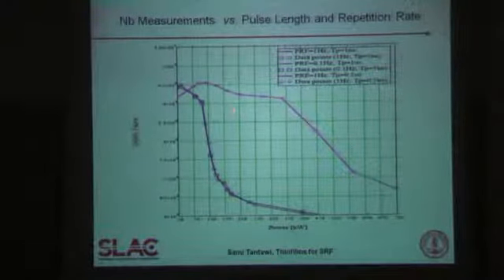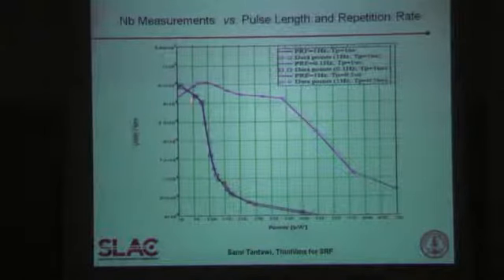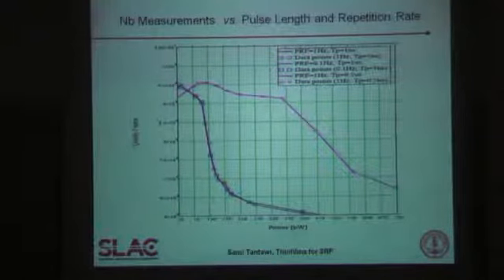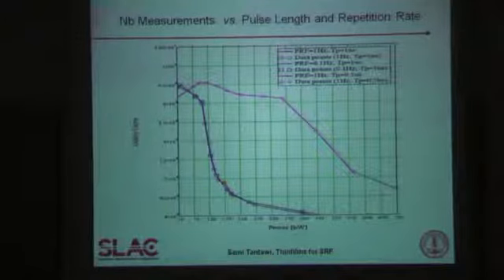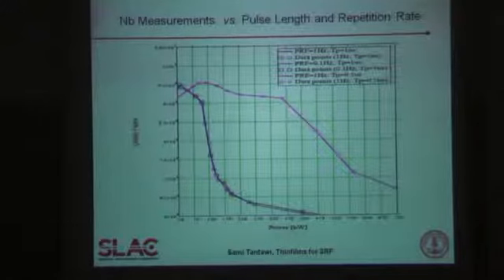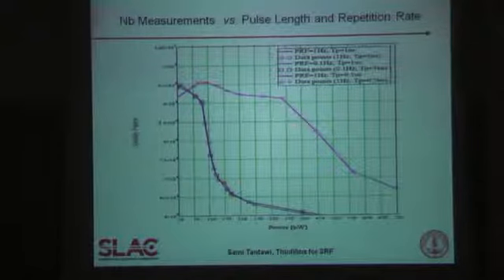At the very beginning of these measurements we observed several things. First, we varied the repetition rate to see if we were heating up the system, and for different repetition rates we couldn't see any real change in the cavity. We also changed the pulse length, and with the pulse length there was a small change but it was not large.